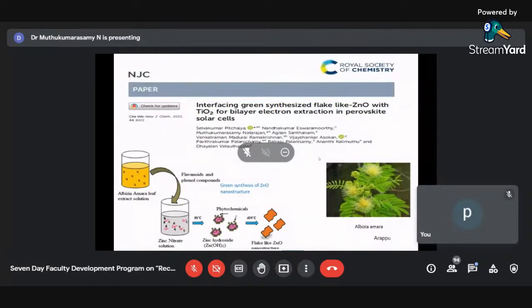And this is another interesting paper which we published in Royal Society of Chemistry. They call it the RSC journal, and we have so many papers published in RSC journals. And here what we did was we used zinc oxide, and this zinc oxide we prepared. Actually, we didn't prepare it directly from this particular plant species. We used this plant species as a catalyst, or you can even say a surfactant, and it controlled the crystallite size of the zinc oxide formation. So the flavonoids and the phenol compounds present in them acted as a grain size reducing agent, and we were able to get very good zinc oxide nanoparticles and flake-like zinc oxide.